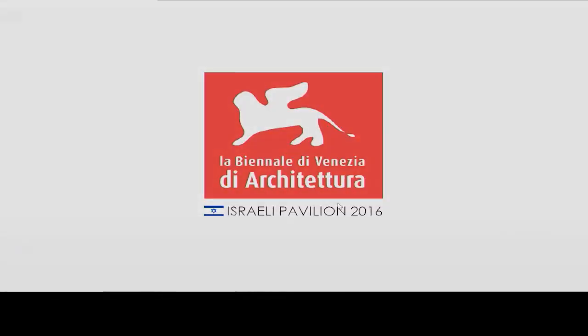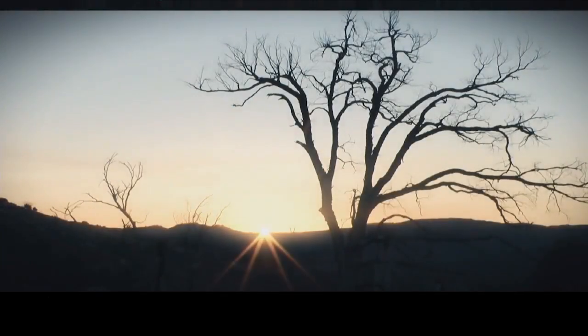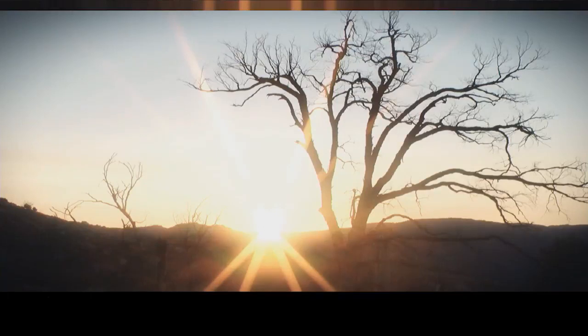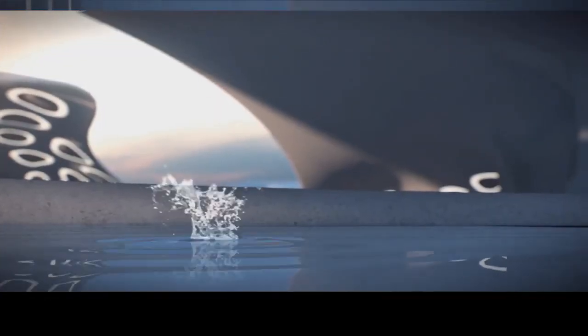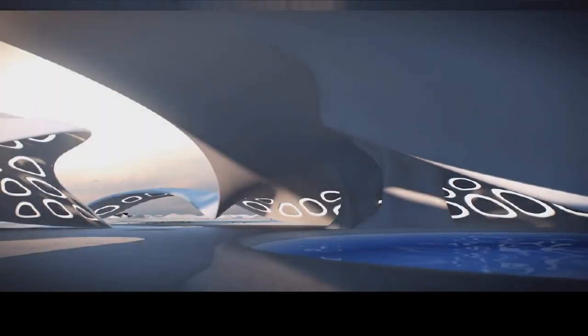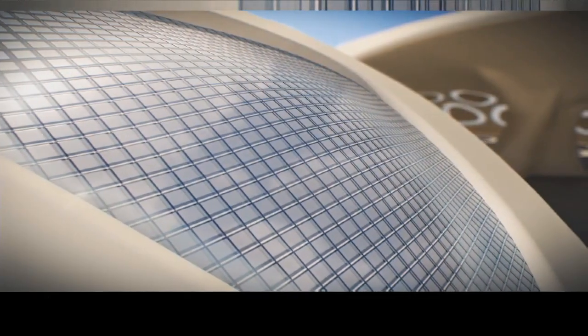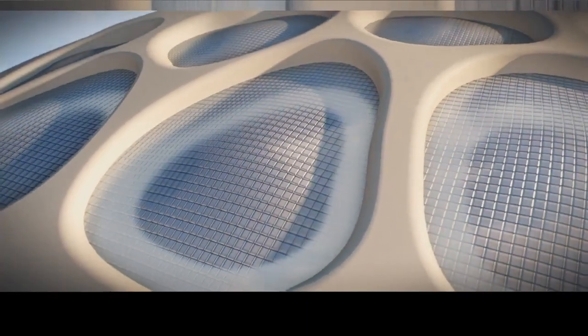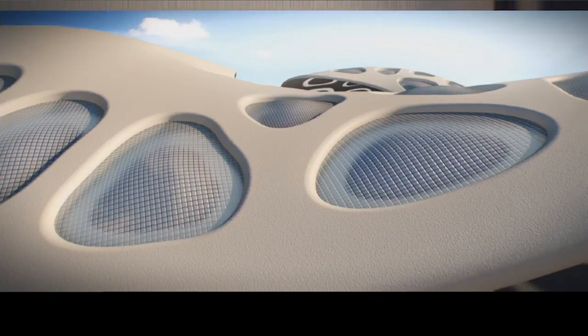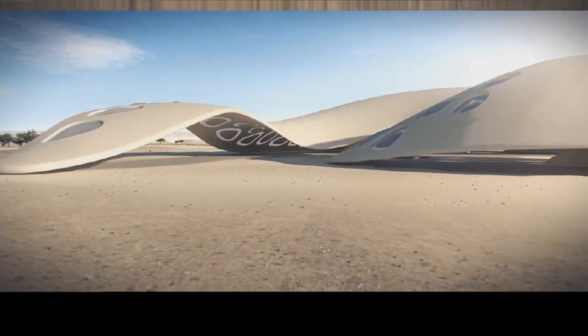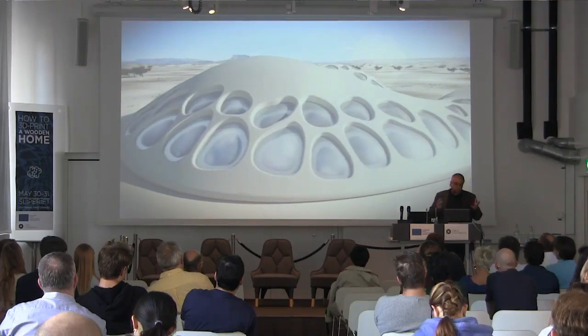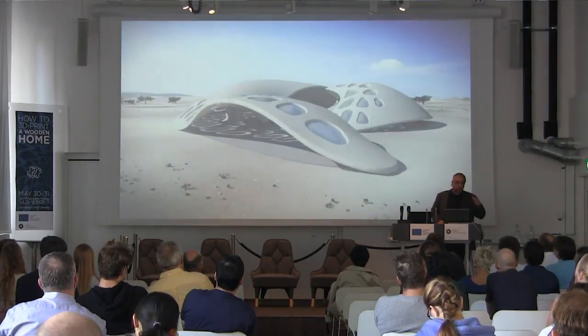So the idea here is to build a shelter in the desert. The first feature is a superhydrophobic coating of nanocellulose that enables us to collect some water early in the morning in the desert from the dew. So we can collect this water into a pond. And of course, as you can see, because it's a self-assembled material, we're not limited by the classic architectural constraints. We can make materials, all nanocellulose based, that are either opaque or semi-transparent.